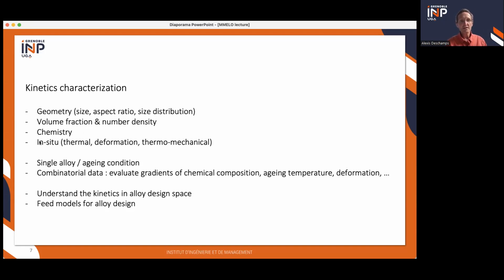And of course, if you want to have the kinetics, so it means the evolution with time or with deformation or during deformation and temperature evolution, it's useful to have it in situ to get the full kinetics, instead of a few points here and there. So usually you do that in a single condition. So you do an in situ experiment on one alloy at one temperature, and then you're doing another alloy at another temperature during one straining condition. And then you add up the experiments, and it can be quite long.